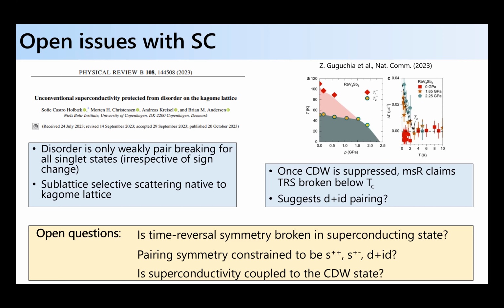This is from μSR again. In the CDW state, because this is the RbV3Sb5 system, when they do their μSR measurement, they cool down, and when you enter the CDW state, they see the muon relaxation do something weird. Then they keep cooling down. But then they apply pressure, and they can suppress the CDW order parameter. When they cool down, they don't see anything happen in this funny change in the muon spin relaxation rate until they cool below Tc in zero field. And so that's kind of odd. From this, they're claiming that maybe there's some time reversal symmetry broken below Tc. If that's true, then maybe D plus iD. I don't know. So it's open questions, but that's speculation.